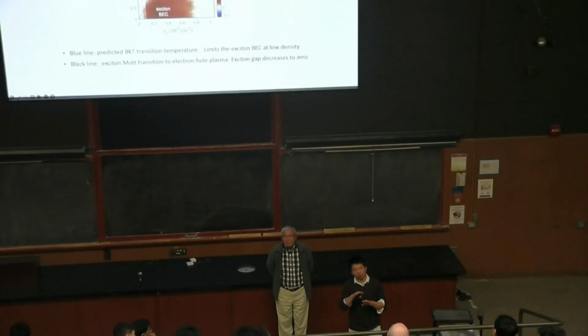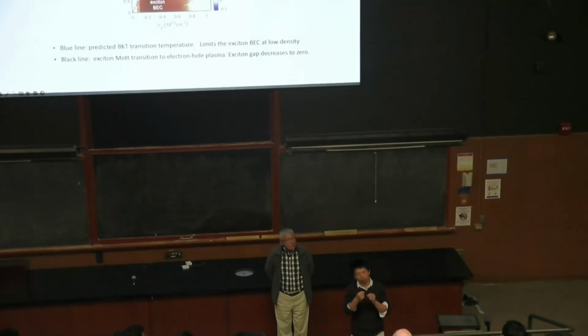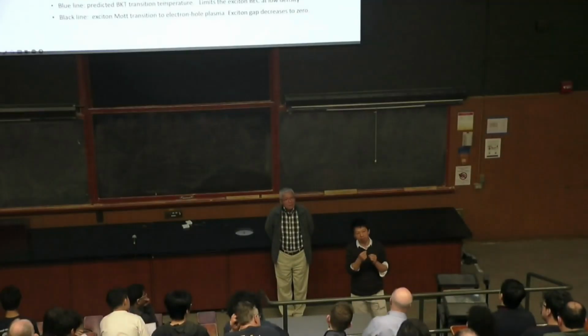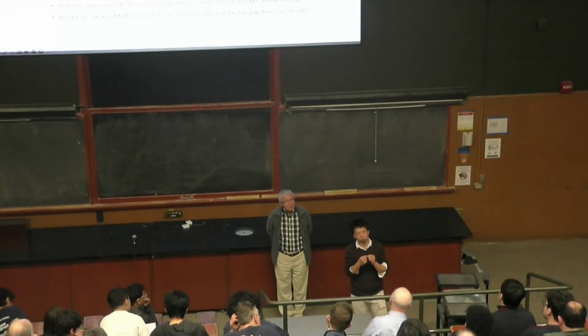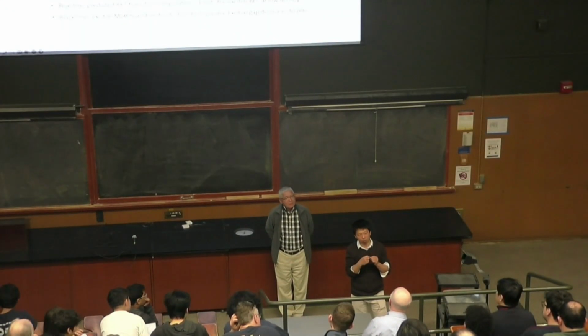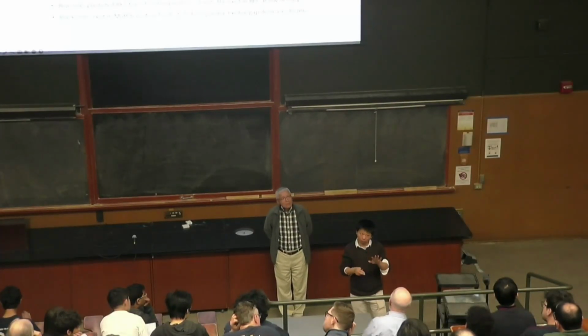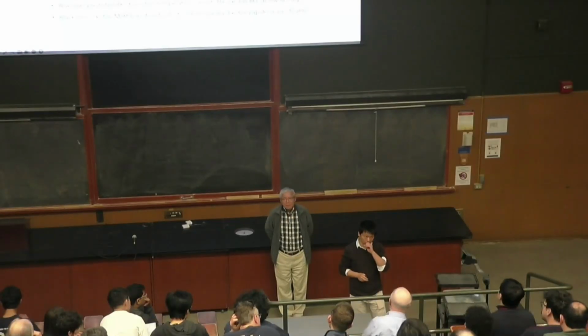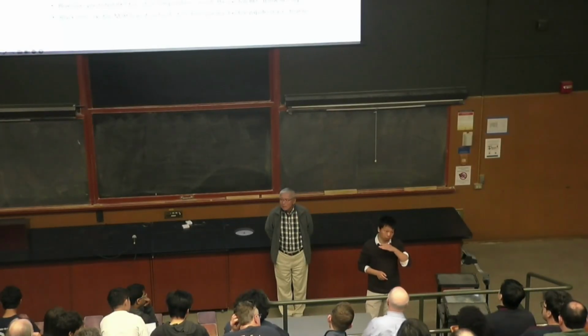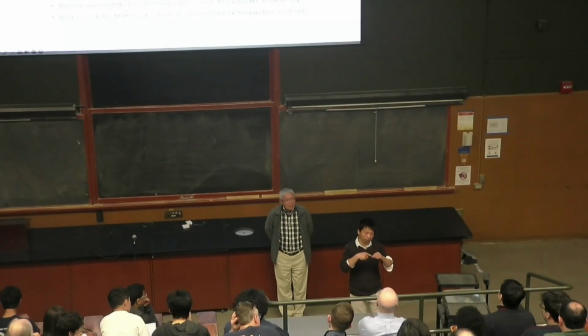And also, if we see their radiation, it turns out maybe the defect is still important. We find that even with the very small leak current that we do see, most of it is still going through non-radiative channels rather than radiative channels. So we are hoping that we can also see radiation. We are maybe pushing the BN to be thinner so the tunneling can be stronger.